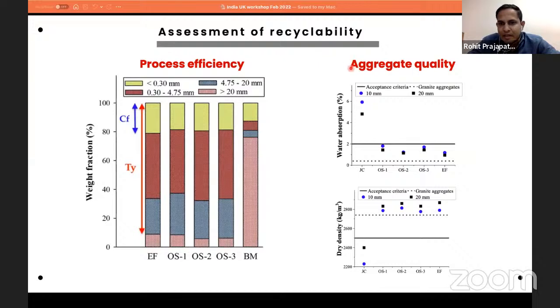Similarly, here you can see the water absorption and dry density. So this black line is the acceptance criteria. So you can see the JC is the jaw crushed aggregates. So these are having higher water absorption, and then all this OS trials from the solar heating and EF from electrical heating are satisfying the acceptance criteria in case of water absorption and dry density as well.